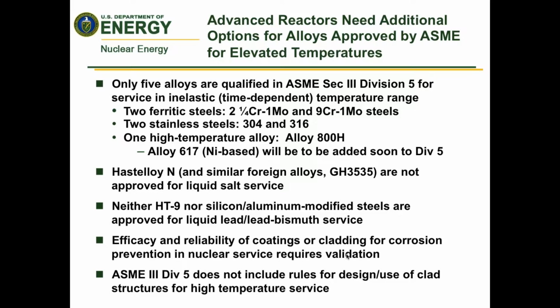Hence, one of the other approaches that people are looking at is putting coatings on to protect the materials that are in the code, or cladding, weld overlay cladding, for corrosion prevention. And those are interesting ideas. However, ASME Section 3 Division 5 simply does not have rules that allow for the use of cladding or bimetallic structures at those high temperature conditions. So something has to be done about that.